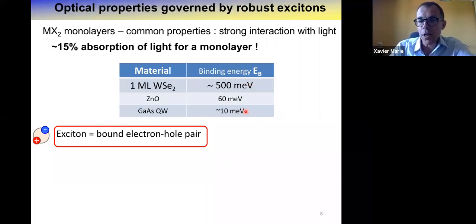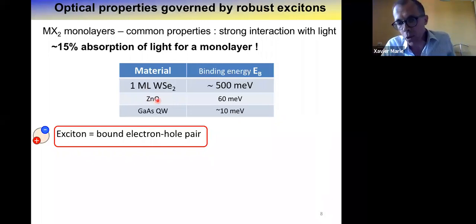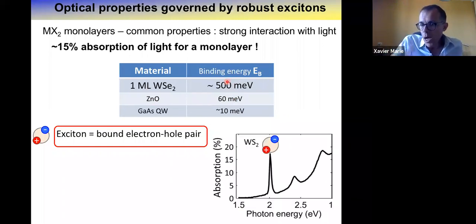Compared to the well-known model system of gallium arsenide quantum well, you see it's one or two orders of magnitude larger. Even zinc oxide, which is known as a material with very large binding energy of the bulk exciton, has a much smaller binding energy here. And indeed, because of these exciton features, which I will describe in a little more detail in a few minutes, you get in an absorption spectrum this very strong resonance associated to the large oscillator strength due to this very robust exciton.